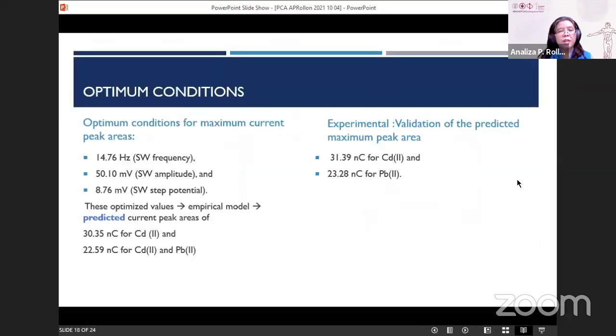And for the optimum conditions, the empirical model was generated from the experiment. The optimum conditions, that means for maximum current peak areas, were 14.76 hertz for the frequency, 50.1 millivolts for the square wave amplitude, and 8.76 millivolts for the square wave step potential. And these optimized values were obtained, of course, from the empirical model.